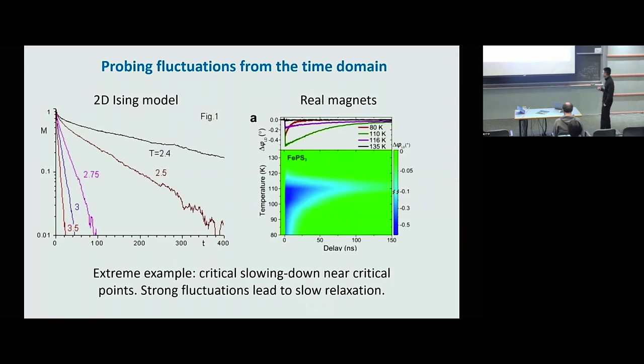So we know that because the fluctuation is very strong, the dynamics is very slow. If you look at the relaxation dynamics of the order parameter, it becomes slower and slower as we approach the critical point. And this can be easily simulated in a 2D model. It's also observed in various types of magnets. So we can see that when we go near the critical temperature, the dynamics becomes very slow.